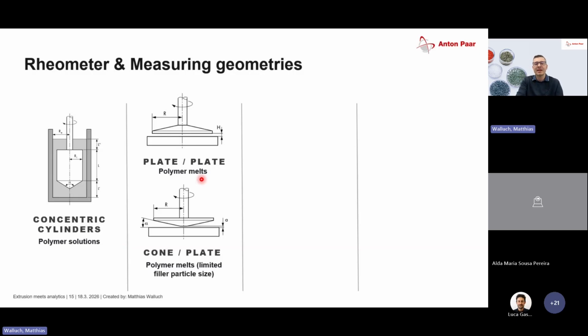The difference is that the cone plate system has the advantage that we only have one shear rate over the whole diameter of the measuring system because of this cone, which is not the case here, but here we are calculating the correct shear viscosity, so we get basically the same results. And the drawback of the cone plate system is that you have a very small and defined gap, and this is probably sometimes a problem if you have a filled material. So here the particle size is important.